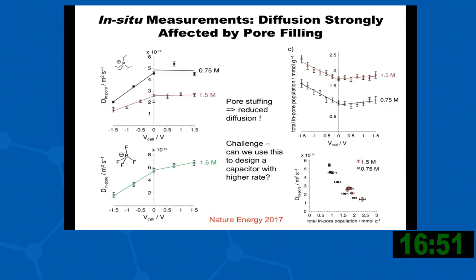What is interesting, though, is we can actually measure transport as a function of state of charge. And what you're looking at here now is the diffusivity of the cations and the anions as you go to positive voltage and you go to negative voltage. And if you remember, I told you in the last few slides that when you go to positive voltages, you swap ions, so the number of ions in the pores stays constant. And what's interesting is the diffusivity stays almost the same. Whereas when you go to negative voltages, when you shove more ions inside the pores, everything's more crowded and the diffusivity goes down. So pore stuffing reduces diffusion.